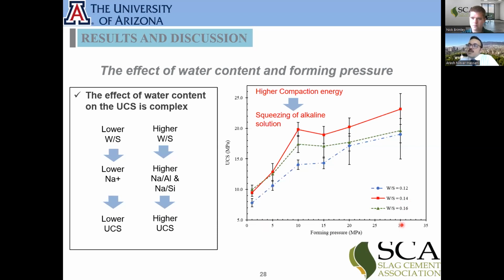We are going to talk about it in the microstructure, why this is happening. But what about the water to solid ratio? In lower forming pressure, let's say 1 megapascal, because the compaction is not that much, by increasing the water to solid ratio from 12 to 14 to 16, the UCS is increasing.